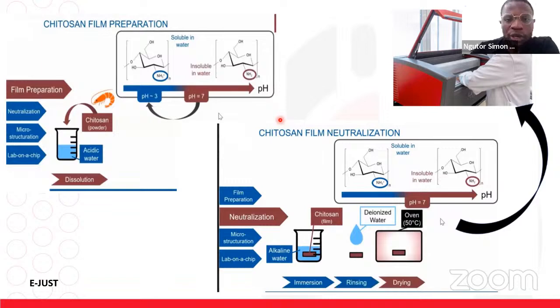So here the target is using a material that is readily available, because most of the materials used in literature are based on PDMS or acrylates. PDMS is flexible, but when it comes to biodegradability, that is where the issue comes from. So we prepare chitosan so that we can use it as a microfluidic chip to be attached to the skin. But as you know, chitosan is insoluble in water.